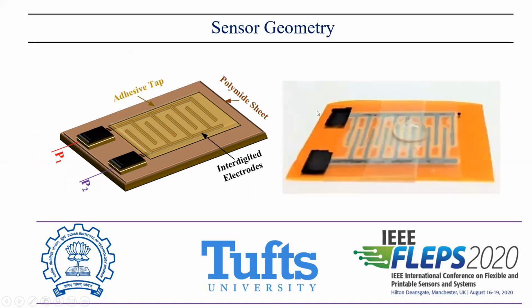Here we can see the actual fabricated sensor with a drop of water on top of it. We can see the polyimide substrate here and the coated interdigitated electrodes on top of it, and the adhesive tape can also be seen on top of the electrodes. The adhesive tape was not placed on the tip of the sensor, to make contacts with the detection electronic circuit or signal conditioning circuit. Of course, the water level is not in direct contact with the interdigital electrodes. So basically, the fringing field between those electrodes is changed because of the water level, which in turn changes the capacitance of the sensor. So the idea is very simple, and the fabrication process of the sensor is also very simple in this aspect.